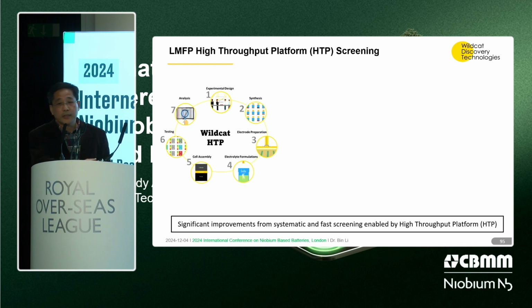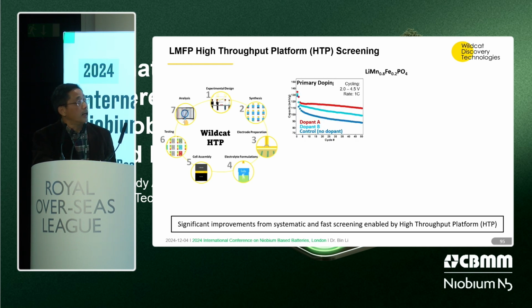Here I just give one example for the lithium manganese iron phosphate study. And in 2012, at that time, we worked on the 80% manganese. Currently, in China, most of them still work on the 60% manganese. Here I give the doping study. We have those baseline, and then doping A elements and doping B elements. You can see that doping does improve both initial capacity and also cycle life.